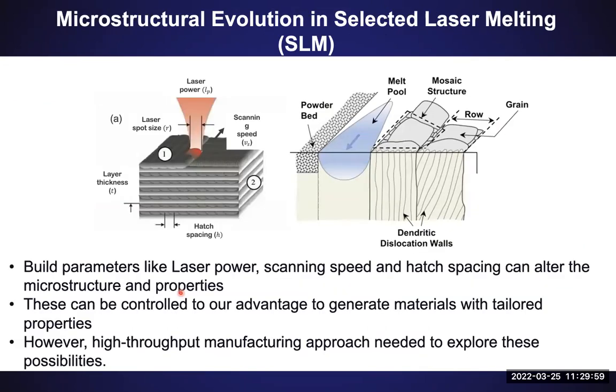Okay, so we were using selective laser melting. And as I mentioned, during this process, there are many different parameters that can affect your microstructure. There are things like laser power, the speed at which the laser scans, and the hatch spacing between the laser passes, basically, that can alter your microstructure. And we wanted to see how, as we change these build parameters, that modifies our microstructure and then eventually affects our properties. There's been a lot of work to look at quasi-static properties of additively manufactured materials, but we were looking at a very specific high strain rate regime behavior of materials, and we wanted to tailor these properties to try to see if we can generate more damage-resistant materials.